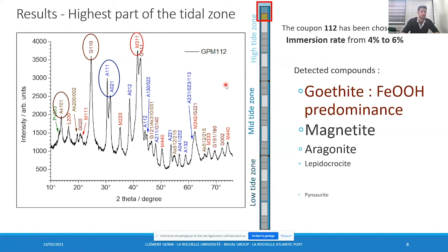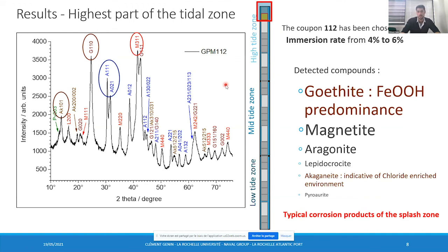Magnetite is still detected, and aragonite is detected too, which indicates that cathodic protection could persist during the immersed phase. Lepidocrocite is detected, and akaganeite is detected too, which is an indicative corrosion product of chloride-enriched environment. Indeed, this corrosion product requires a source saturated in chloride environment to precipitate, which occurs during the evaporation of the droplets in the splash zone. According to this feature, we could suppose this sample is exposed to the splash zone and with some, really rare, efficiency of the cathodic protection during the immersed phase.